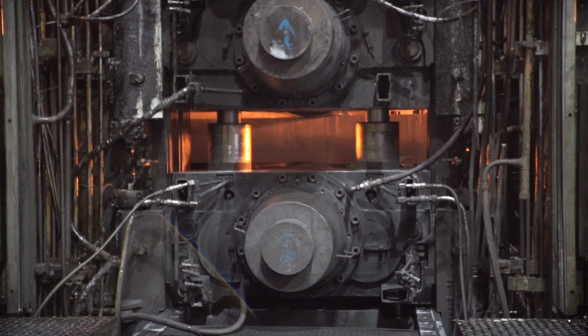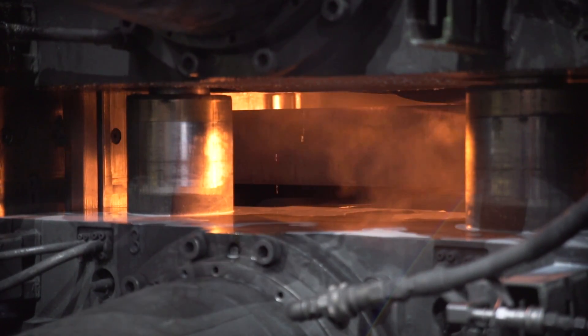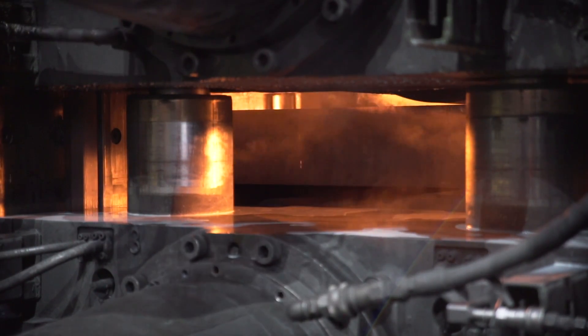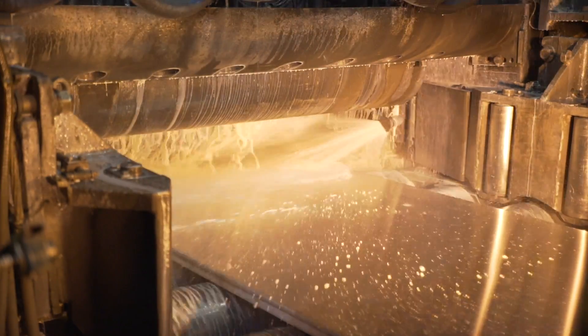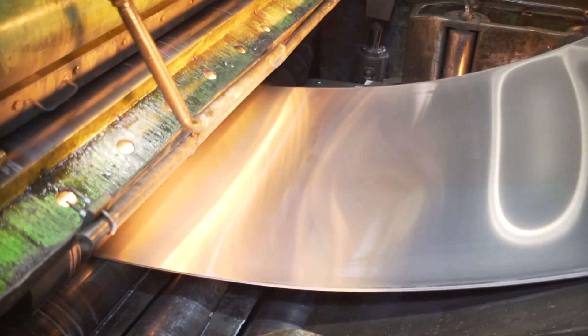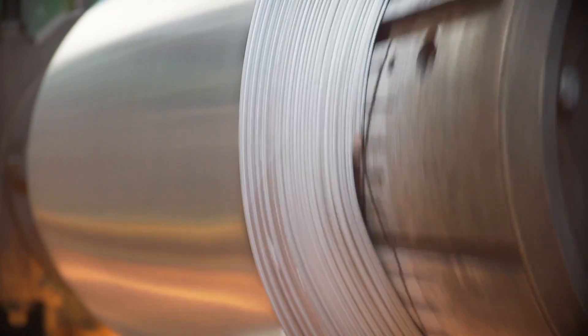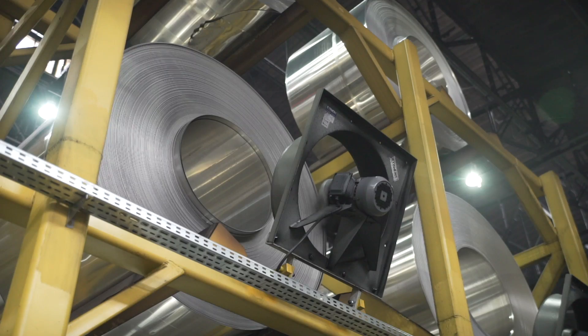The rolling mill is equipped with two backup rolls and two work rolls. During the hot rolling process, slab thickness is being reduced from 390 millimetres down to a final range of 3.5 to 9 millimetres. After hot rolling, the strip is coiled and taken to the storehouse where it needs to be cooled down.